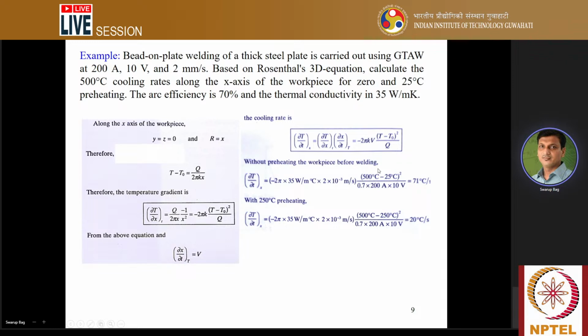And T minus T0. Here it's mentioned to calculate the 500 degree cooling rate. That means at 500 degree, what can be the cooling rate. So the T variable is given. T variable is 500 degree centigrade minus T0. The 0 preheating means that we are not preheating the sample, rather we keep it at the ambient temperature. In that case, T0 may not be exactly 0. The T0 should be the ambient temperature, so you can assume it's 25 degree centigrade. That's why we have written 25 degree centigrade.